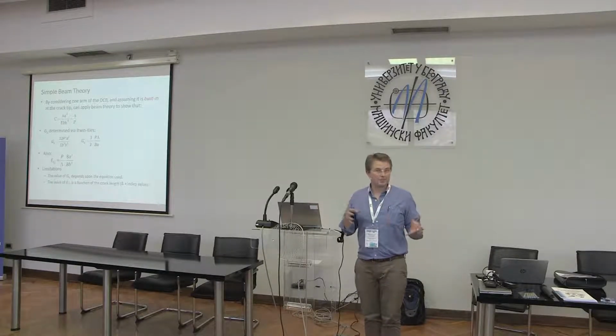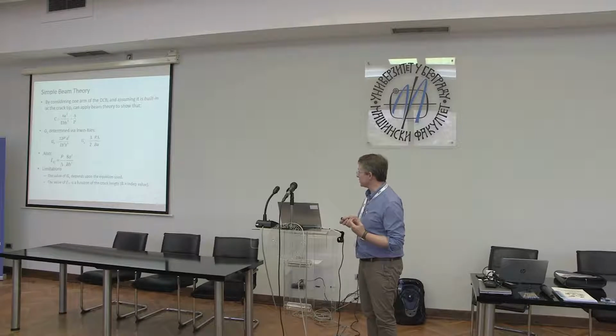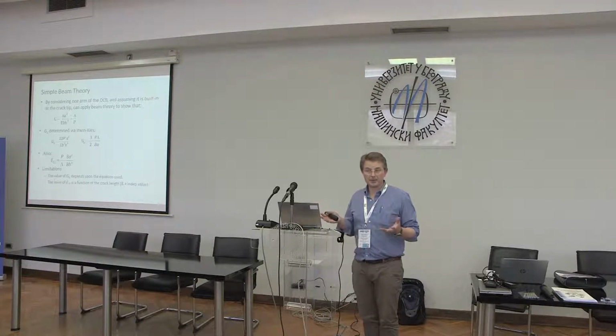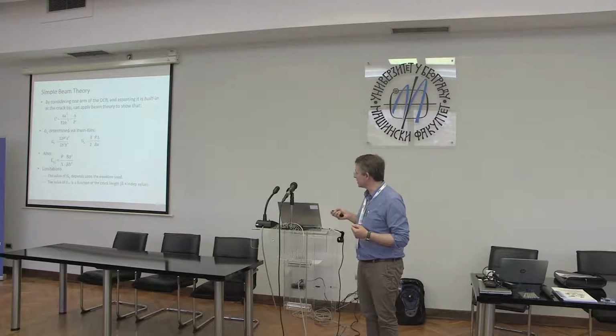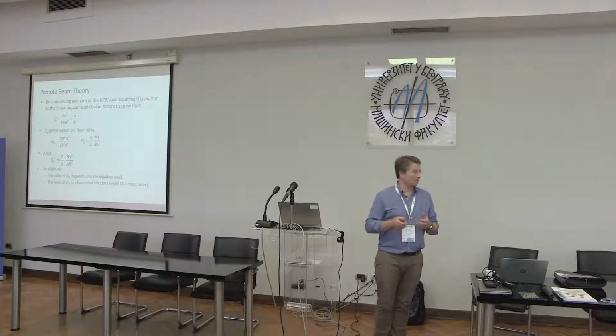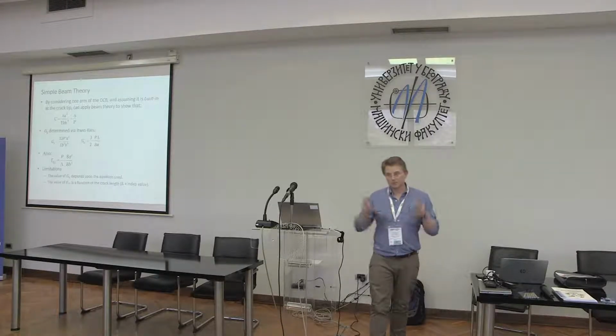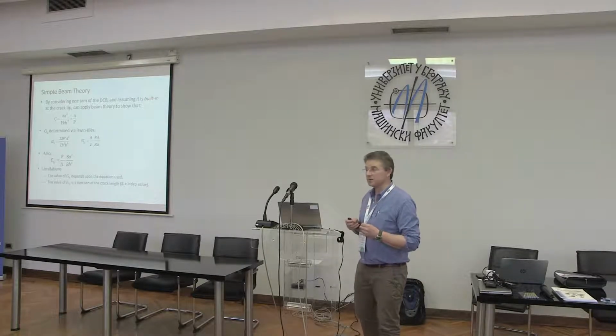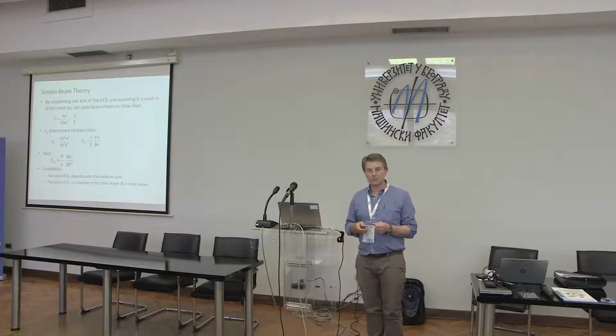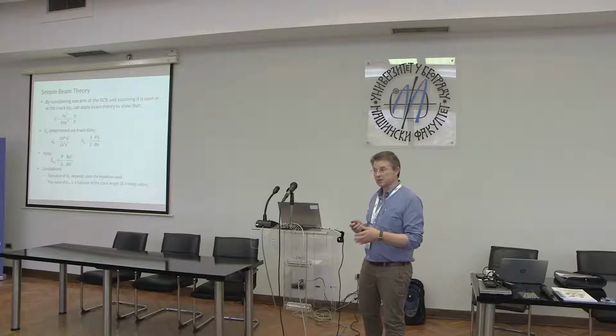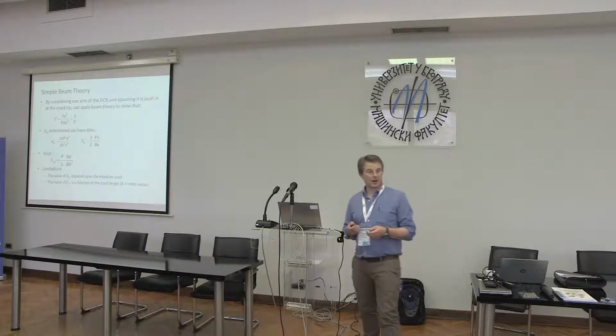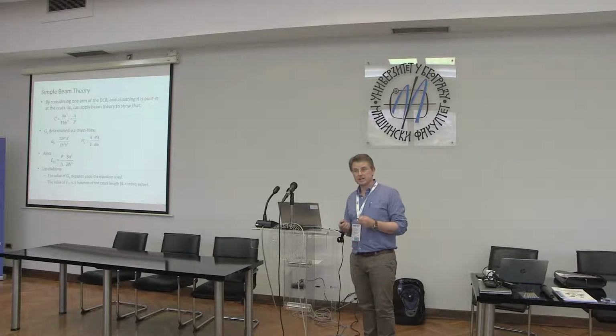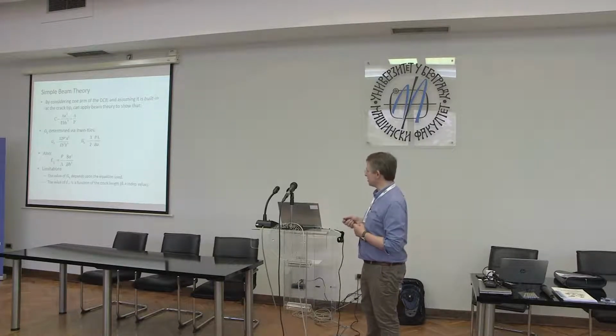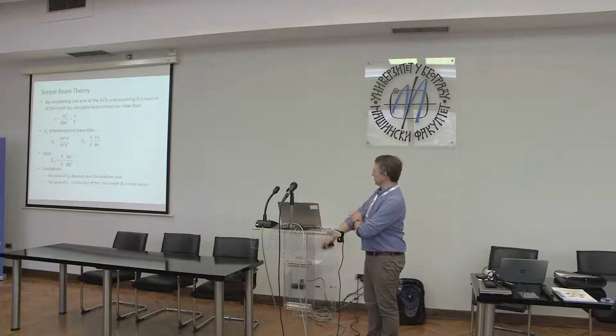The fracture parameter can be measured via simple beam theory. I won't go through all the details of it, but we assume, for example, a cantilever beam is built in perfectly at the crack tip. This is assumption number one. And then we can derive an expression for the compliance of that based upon beam theory. And then if we know the compliance, we can determine the rate of change of compliance with crack length, which is that critical parameter you need for the Irwin-Kies fracture mechanics expression to determine an energy release rate. So we can easily determine an energy release rate based upon our experimental data from such a test.